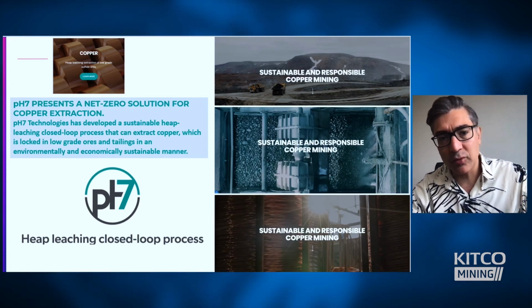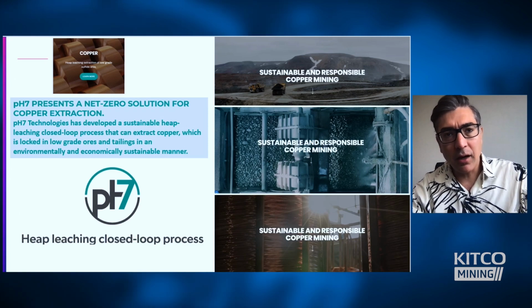So everything is happening through the extraction of the copper from the copper sulfide through flotation concentration, and then shipping overseas to smelters and melting down the sulfide copper concentrate to extract the copper. What we are offering, and what we have been focusing on for the last 2 years of R&D, was enabling the heap leaching process, which is happening in oxide ore, for sulfide ore. Heap leaching is a very low cost, environmentally friendly process that doesn't need really fine grinding. You just have a jaw crusher, and after the first crusher, it can go to a heap leach and you circulate your chemistry through it.